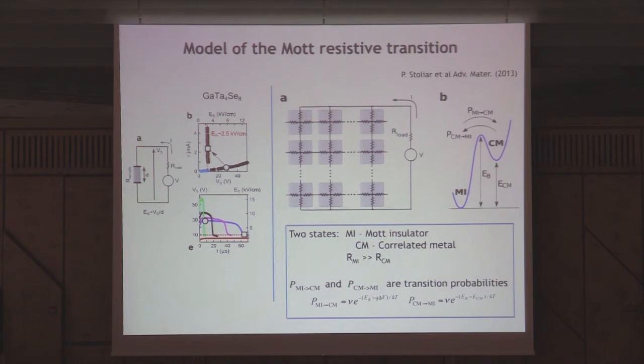There are resistor networks of all sizes and shapes. Everything is defined by your assumptions for the resistance. So our assumption is that we have two states. The lower state, the most stable state, is a Mott insulator, which has high resistance and is more stable. And beyond an energetic barrier, you can access a metastable state, which is a correlated metal. But since this is metastable, it has a higher energy, and of course has a barrier to relax back to the Mott insulating state. So the additional assumption we made is that on these cells, when you are in the insulating state, you will have some local voltage drop, and that the probability of going beyond this barrier can be increased by lowering the barrier with the applied voltage.